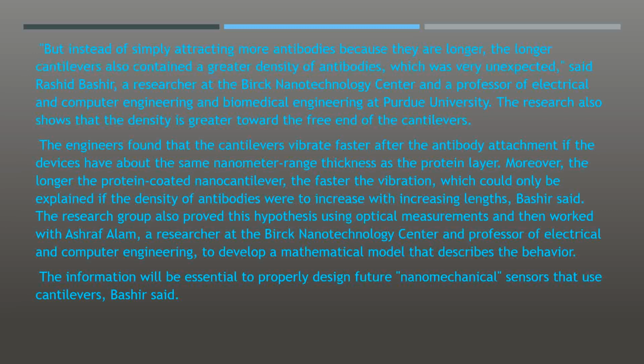The engineers found that the cantilever vibrates faster after the antibody attachment if the devices have about the same nanometer range thickness as the protein layer. Moreover, the longer the protein-coated nanocantilever, the faster the vibration, which could only be explained if the density of antibodies were to increase with increasing length, Bashir said.